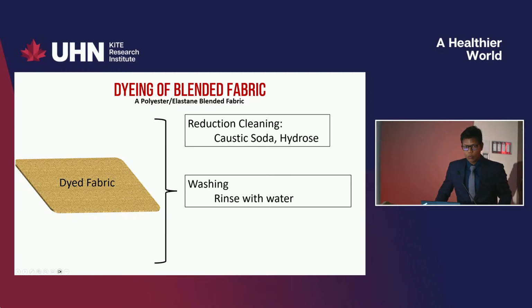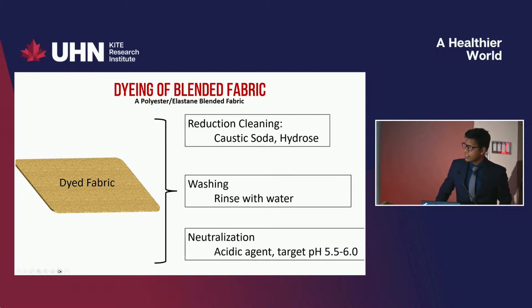Then we do the washing with normal water without any detergent. And then we bring the fabric into an acidic range again, because with the caustic soda during the reduction process, we increase the pH level. With the neutralization, we target a pH of around 5.5. And if we are satisfied, we drain out all the water, and the fabric is good to go for the drying process.